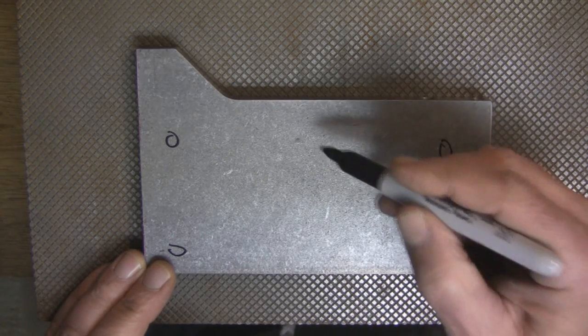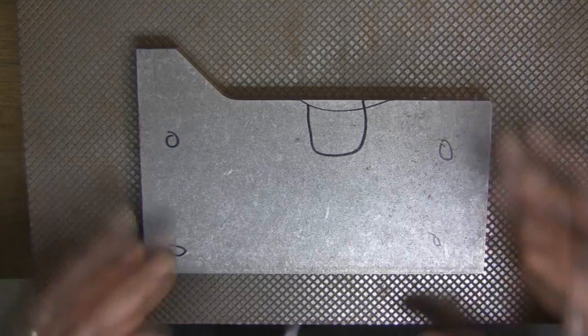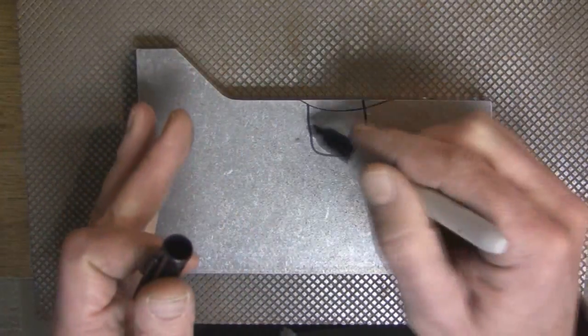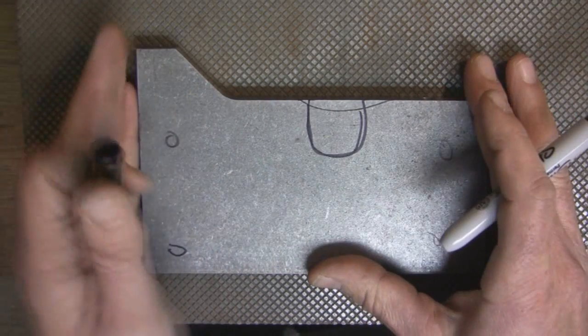But as soon as you do what I just did here, or take a slot, the next morning, this plate's going to go either this way, or this way. It's either going to close that slot, or open. It doesn't like having that skin removed, and what I did is I cut into the skin. It's like peeling a banana.